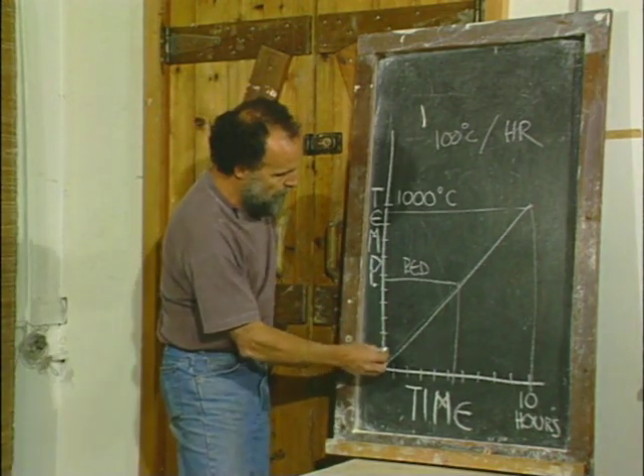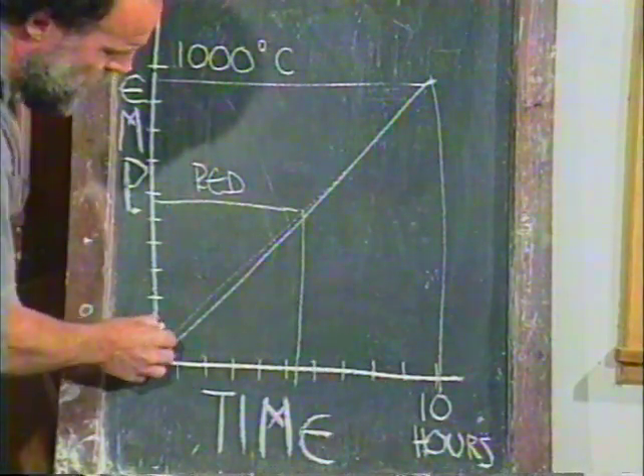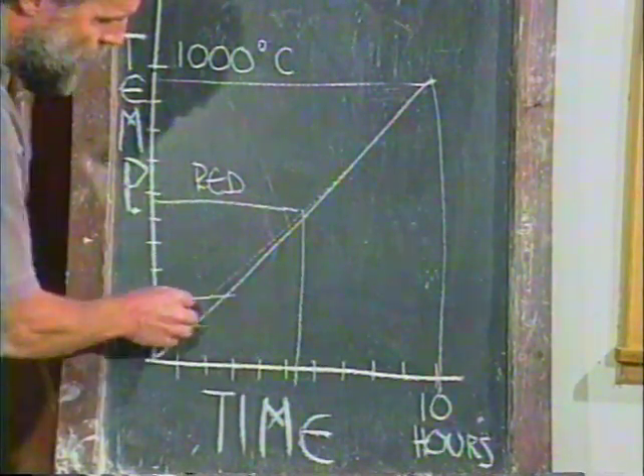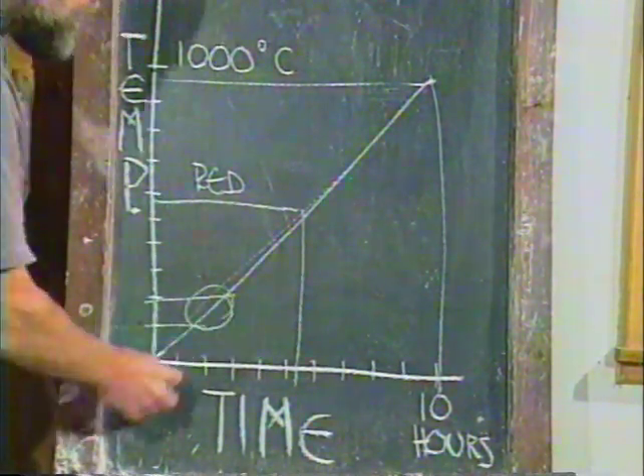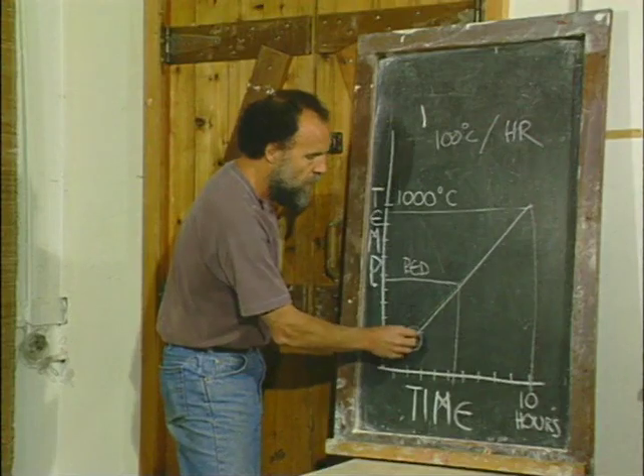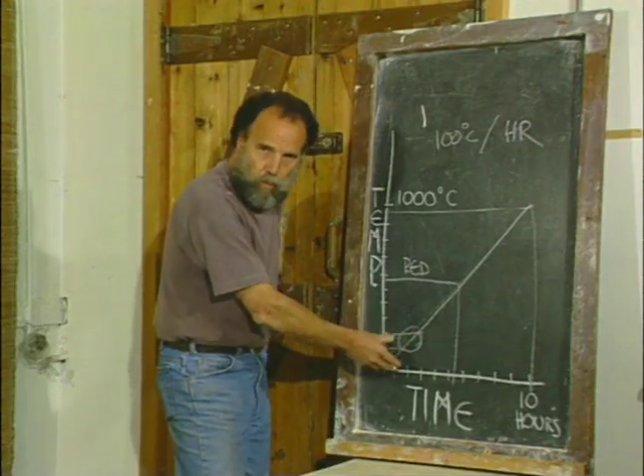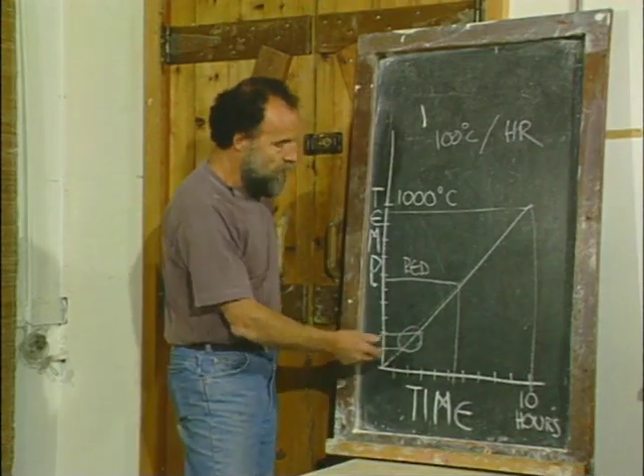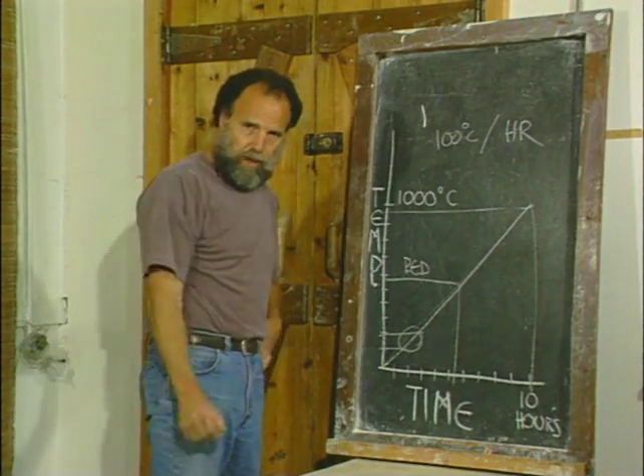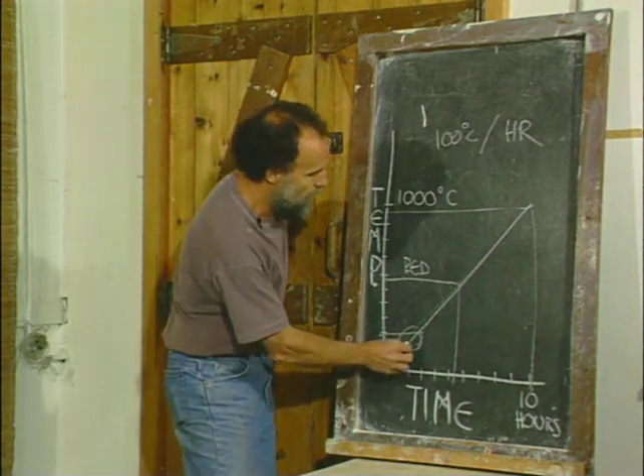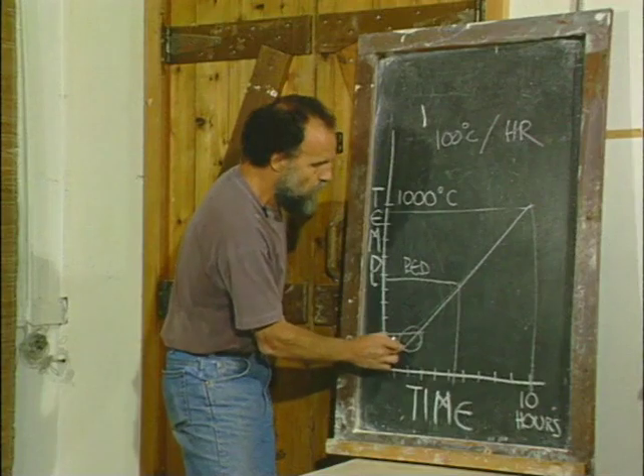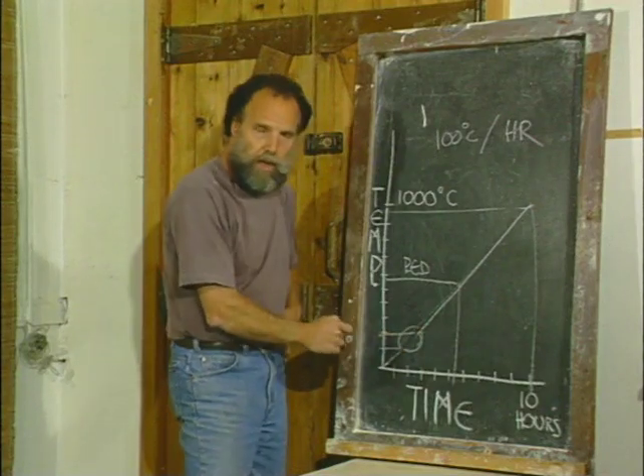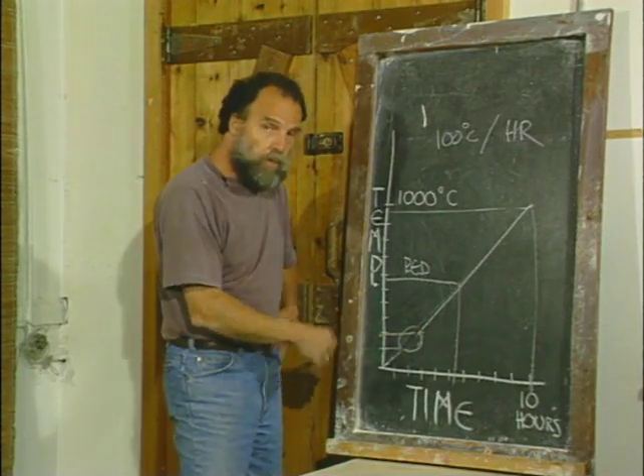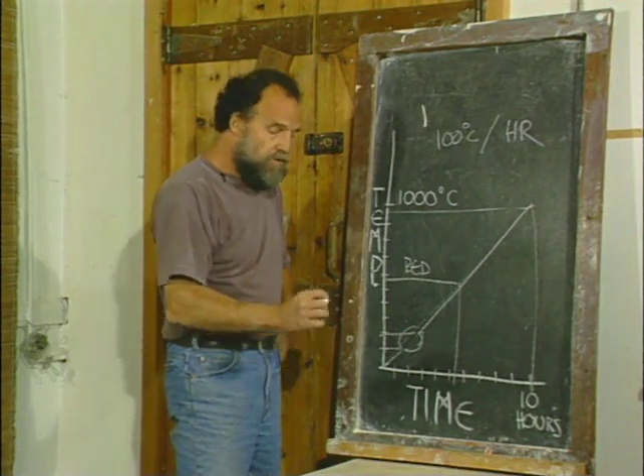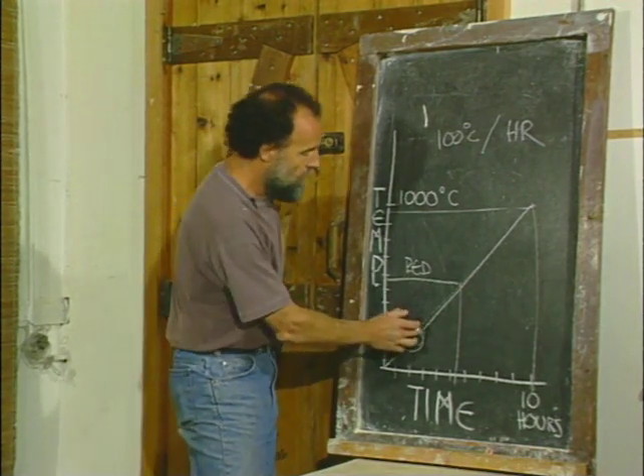What you've got to be careful about is between 100 and 200, this area here, so between the first and the second hour. This will be the zone where most of the water is being given off by the clay from the pots in the kiln. So it's very important that you don't go through this stage of the firing too quickly, because that's when explosions from steam inside the clay body will result.